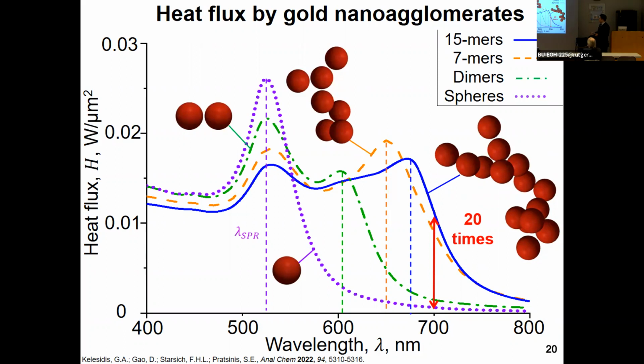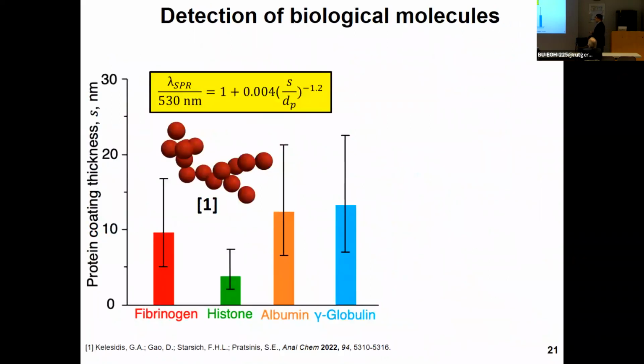Now, these gold nanoparticles can also be used to monitor molecules that have biological applications. So what is done commonly is to mix gold nanoparticles in a solution where proteins are present, but we don't know, for example, the length or the dimensions of such proteins. So in these conditions, what is happening is that the gold nanoparticles agglomerate and they form these clusters that I showed you earlier. But we have a gap in between them because of the coatings with proteins.